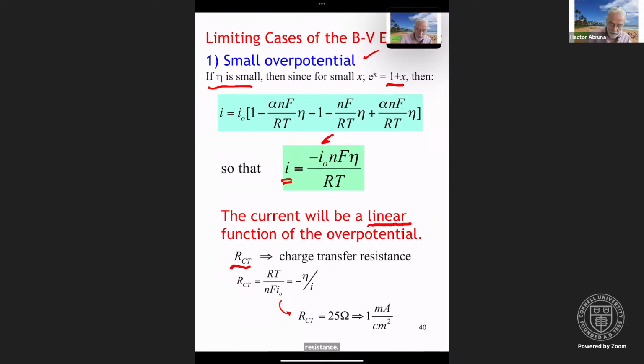And so we have NFI0 that comes from the expression that we saw above. And so the charge transfer resistance, RT over NFI0, if you do it dimensionally, this is voltage and this is current, so E equals IR. And so the charge transfer resistance is sort of a crude measure of the kinetic facility of your process. And just for the sake of argument, a charge transfer resistance of 25 ohms corresponds to a current density of 1 milliamp per square centimeter.